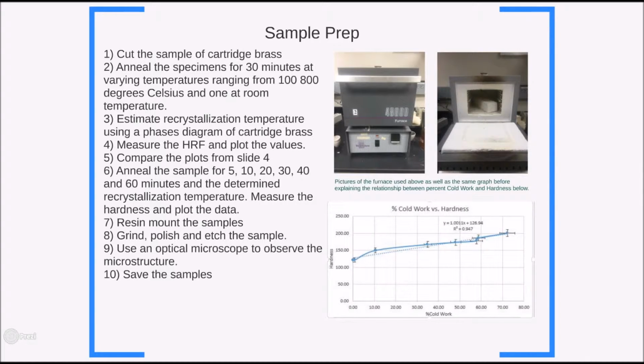Compare the plot from slide 4 using the data from the previous lab. Anneal the sample for 10, 20, 30, 40, 60, and 5 minutes and determine the recrystallization temperature. Measure the hardness and plot the data. Resin mount the sample and carry out grinding, polishing, and etching of the sample. Using an optical microscope, observe the microstructure. Save the samples after observation.